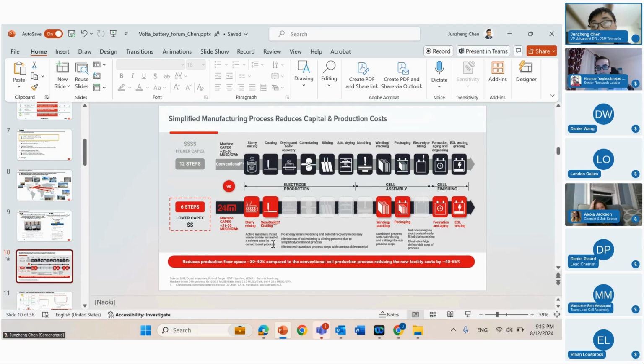So I cannot show the video because of confidential information, but in general, we pass all the EV required tests. And also things like shock and vibration, tear down, that type of tests. So cohesiveness at the beginning of the production and during the cycle is no problem. And then after the formation, after the SEI formation, there are more chemicals, more organic chemicals that can serve as the bonding chemicals. That part will step in. So then you will see better and better adhesion, especially on the anode side.